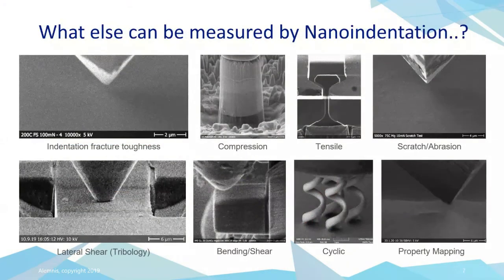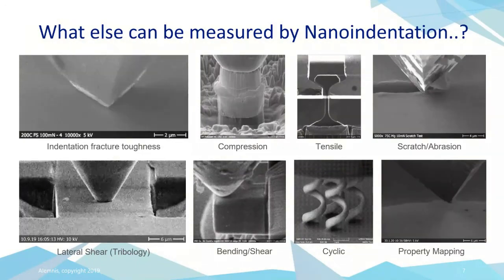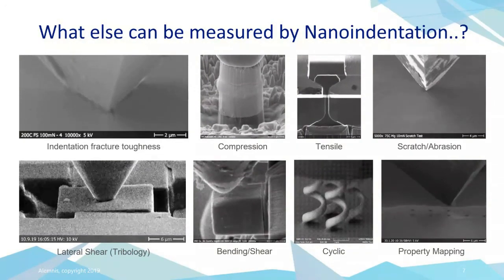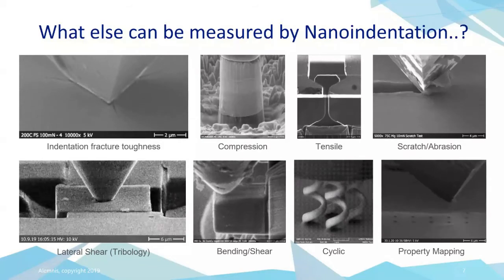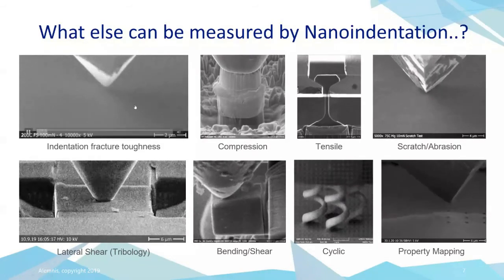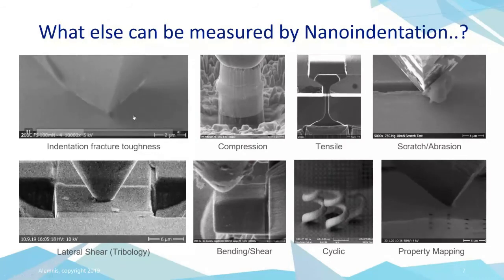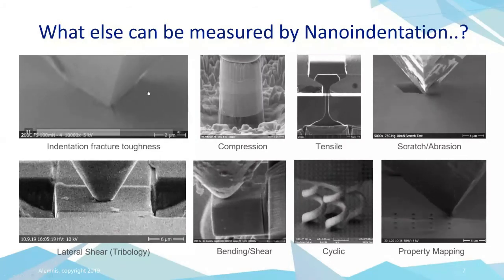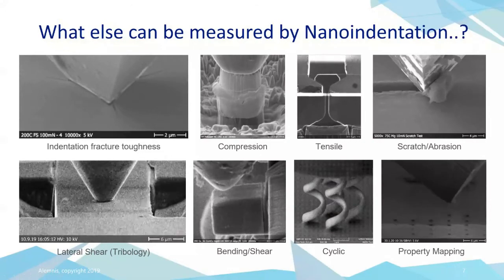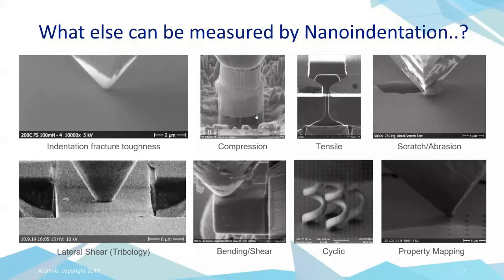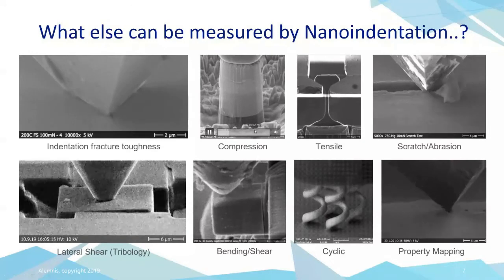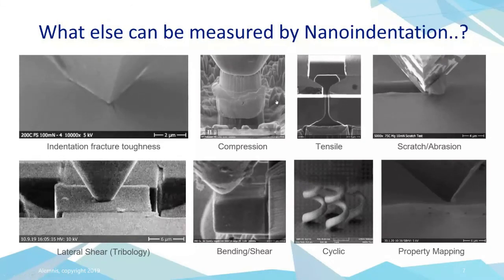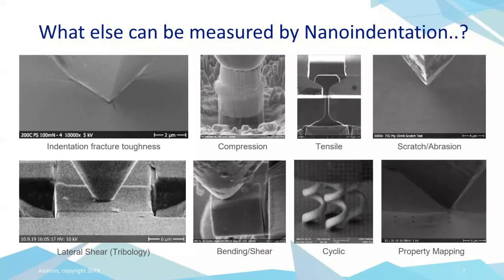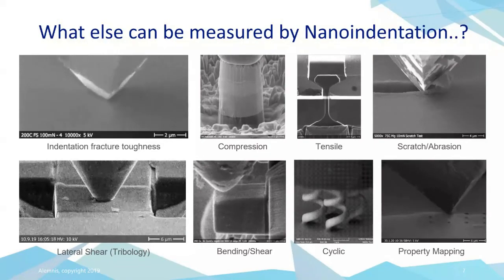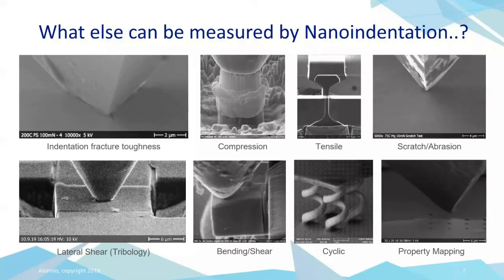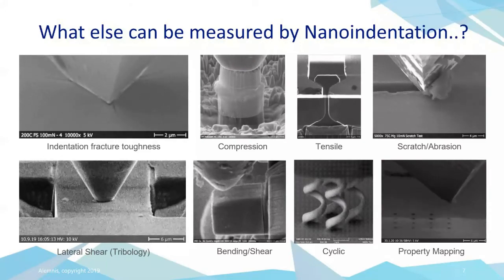Now, nanoindentation is not just used for measuring hardness and modulus. It's a very varied technique that encompasses many different disciplines. You can see here some examples. So top left, we've got fracture toughness. So we're doing an indent here to cause cracking in the material. And from the crack lengths, we can calculate toughness or fracture toughness. Here we've got some pillar compression testing. So a lot of people are using nanoindentation in the SEM to do pillar compression tests. So this is a very interesting field because you can isolate a very small volume of material and understand how it deforms.